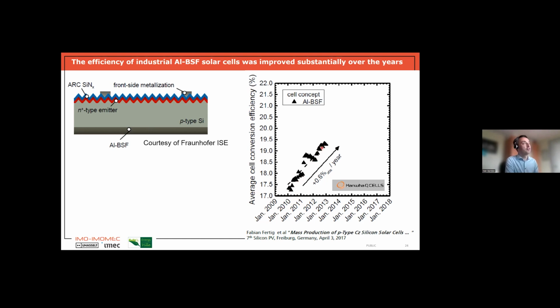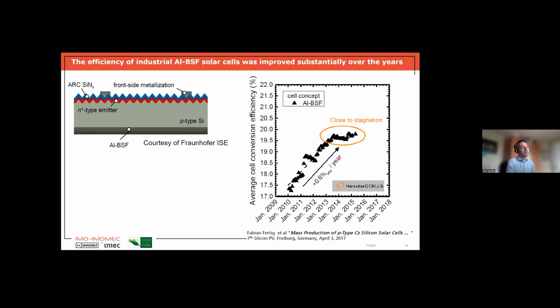How did they increase the efficiency? They just optimized the process. They started using better materials, for instance, better wafers and so on. So they optimized step by step everything they could. And that went pretty linearly. So you can more or less discern here an increase of 0.6% absolute per year. But at some point, the efficiency stagnated. So it seems you cannot really go above 20% with this cell concept. And it's not only in this company, of course, also in other companies, we see that.